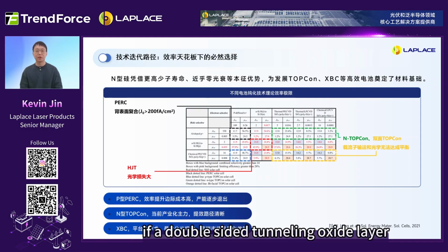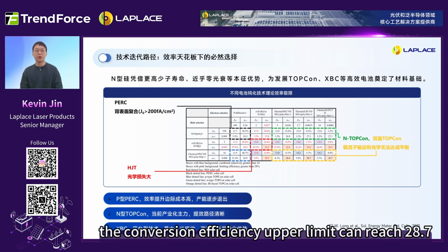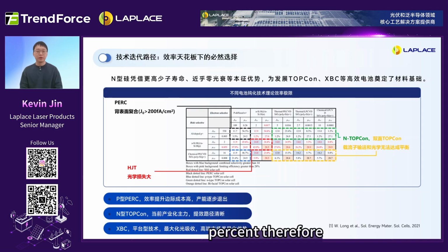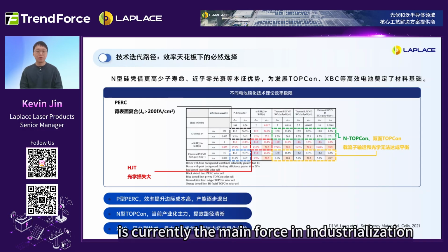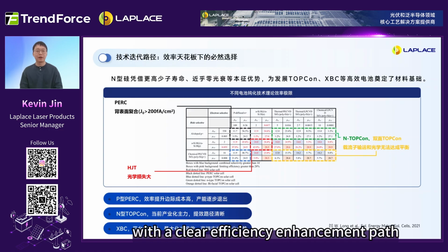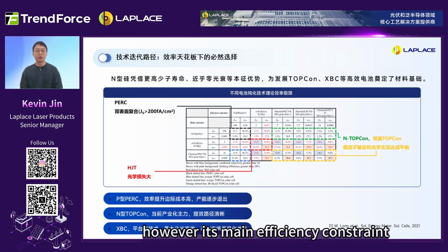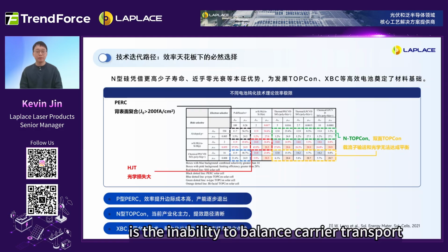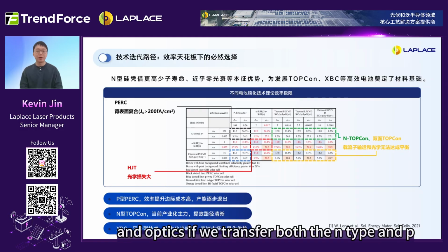For TOPCon cell technology, if a double-sided tunneling oxide layer plus polysilicon layer passivation is used, the conversion efficiency upper limit can reach 28.7%. Therefore, N-TOPCon is currently the main force in industrialization, with a clear efficiency enhancement path. However, its main efficiency constraint is the inability to balance carrier transport and optics.